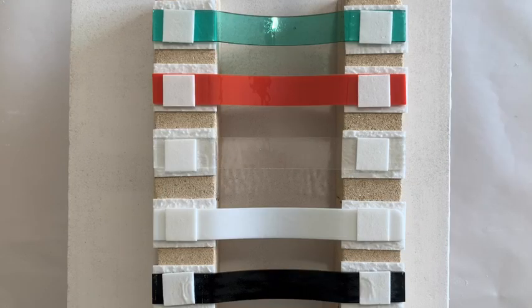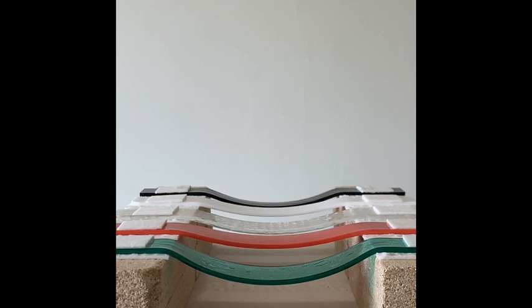It's easy to see how the glass colors respond differently to the same amount of heat and time in the kiln. From this angle, you can see these differences more clearly. The transparent blue slumped the most, followed by the clear and black. The white and opaque orange experience the least amount of slump. The differences in slump are based on the glass viscosity. The higher the viscosity, the less the glass has slumped.